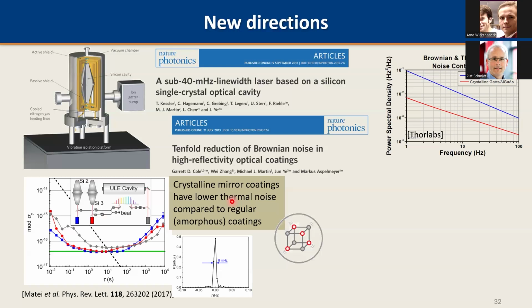Solve it. Would it make sense to go to even lower temperature? I know that's what people now do. But apparently, if I remember correctly, that noise is still present at lower temperatures. But you also cannot go to very low temperatures because you will always put some heat in from the lasers. But that still works, I mean, you can go to millikelvin. But I think that's not necessary. If you go to liquid helium, 4 Kelvin, that should be sufficient to freeze out the thermal noise, and that's what people actually do now. They go back to amorphous coatings, but go to colder temperatures.